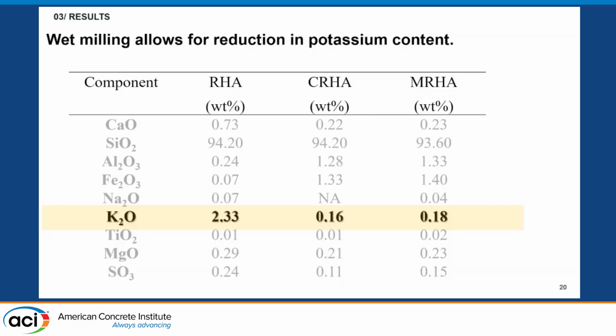level. And something that I'm exploring further right now as well is the fact that rice, when you're getting it from wherever, depending on the season that it's grown, depending on the location that it's grown, depending on also how it is burned at the energy plant, because when you're getting it from the energy plant, you don't have the luxury of kind of changing the conditions in which it's being burned. It's just being burned for energy and that's it. The hope here is that this can also kind of homogenize the chemistry of the material by that milling process.